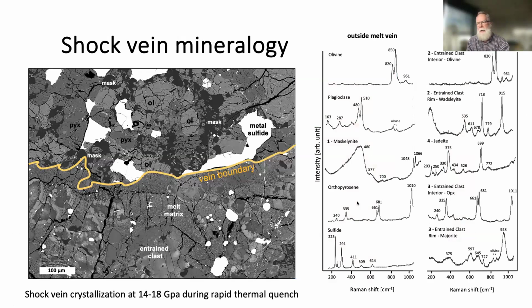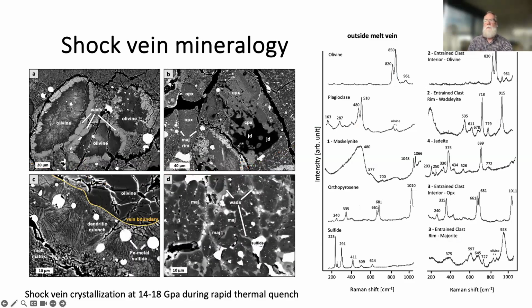So here's Mbale again. This is the sample that we analyzed. Actually, it's the matching slice. And it's got a big melt vein with high pressure minerals. So above is the host, and we've got a lot of maskelynite outside of the melt vein in the host. And then down here is the melt vein with fine grain matrix, and then it's got coarser minerals. So for example, these are the olivines. They have olivine cores and wadsleyite rims. And you can see the wadsleyite is richer in iron.